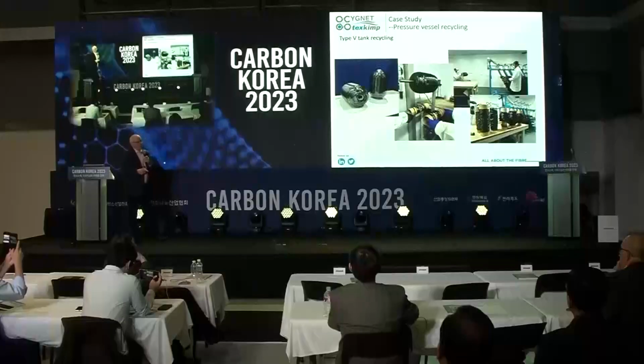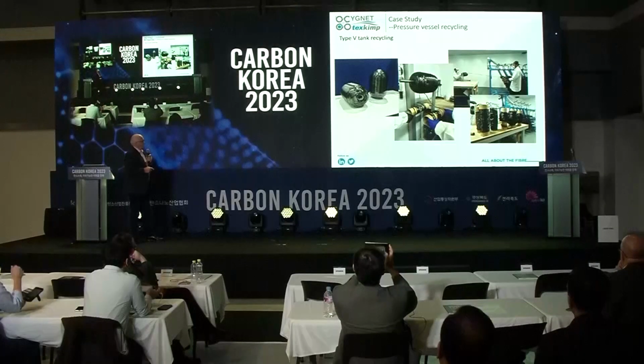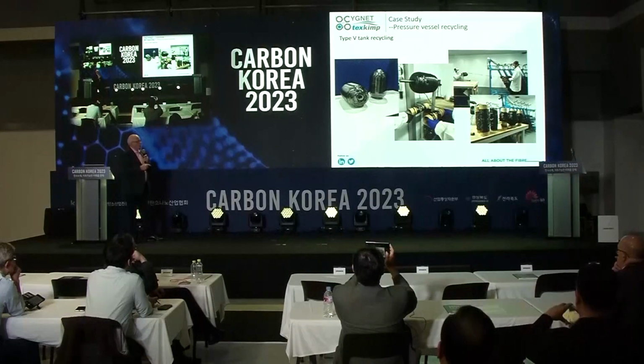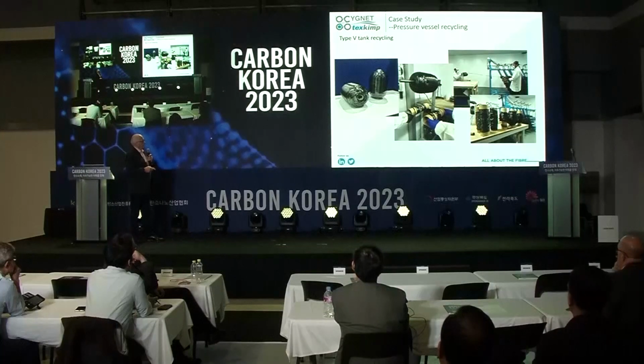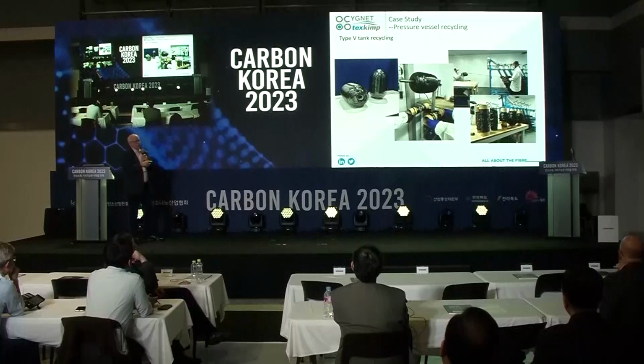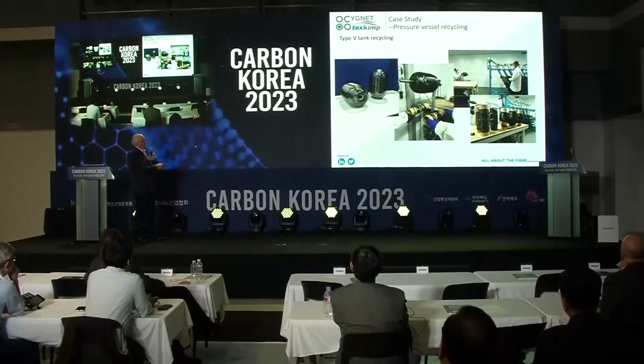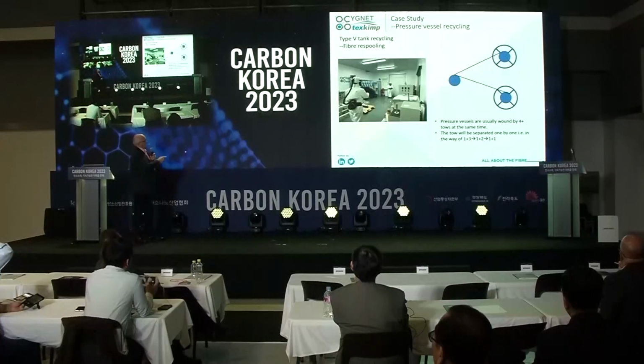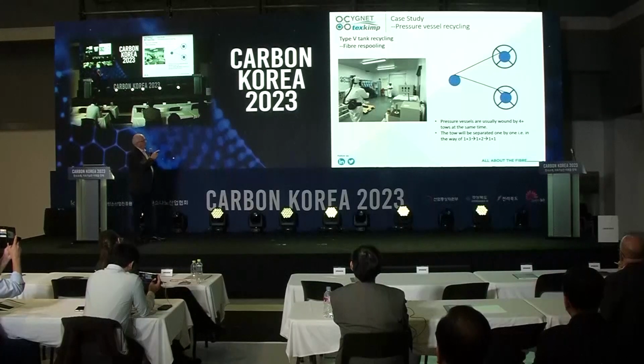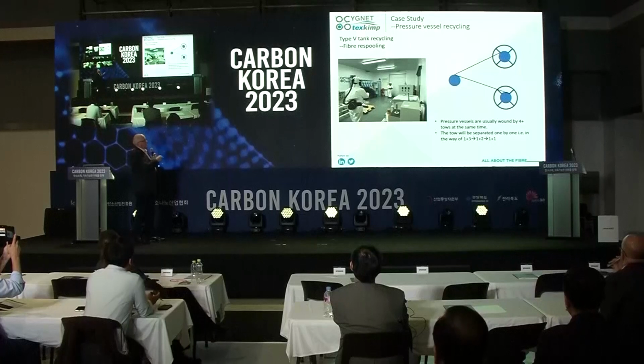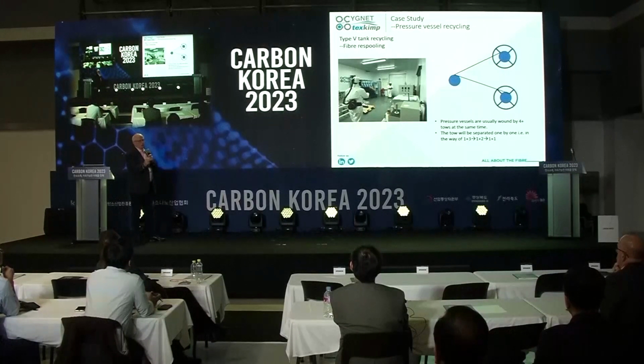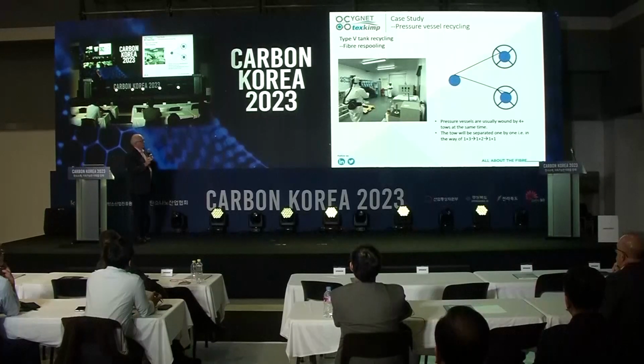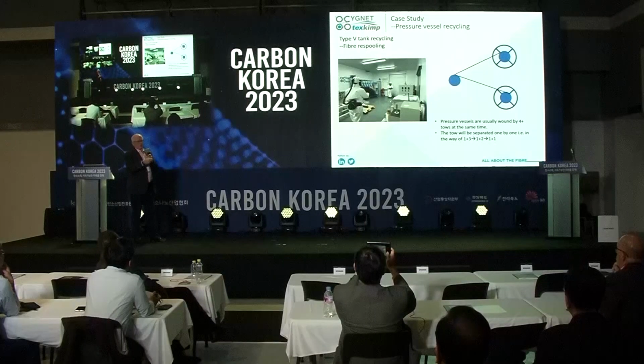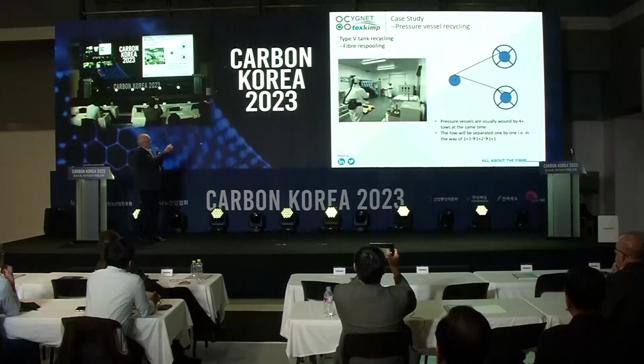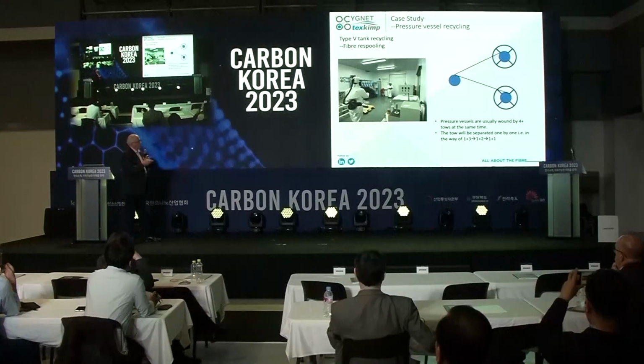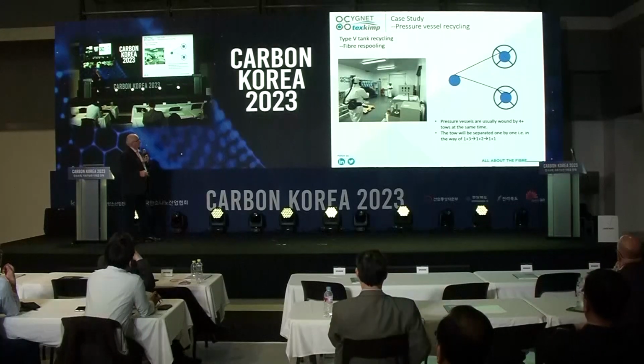But we also tried a Type 5 tank. Now, Type 5 was a bit more of a challenge because, of course, there's nothing inside supporting it. So we did the same sort of thing. We put it into the decom system, recovered the tows, poor souls up there having to suffer that. And one of the interesting things that we found is that obviously we want now to automate this process. And part and parcel of that is that the way cylinders are wound tends to be in courses of 4, usually, although we have seen some variations on that. So the idea here is to recover each tow singly at a time to make sure that we're getting distinct tows. So we're devising, like I say, an automated or mechanical system to do away with people having to do the unwinding.